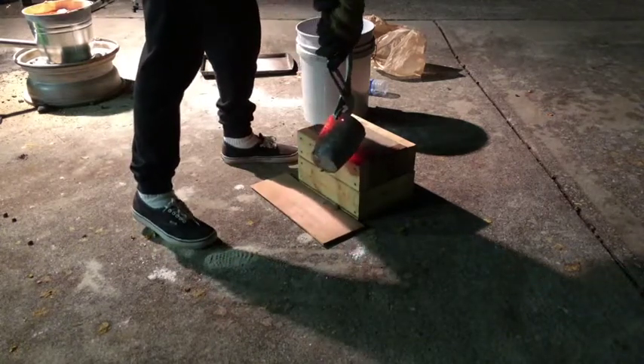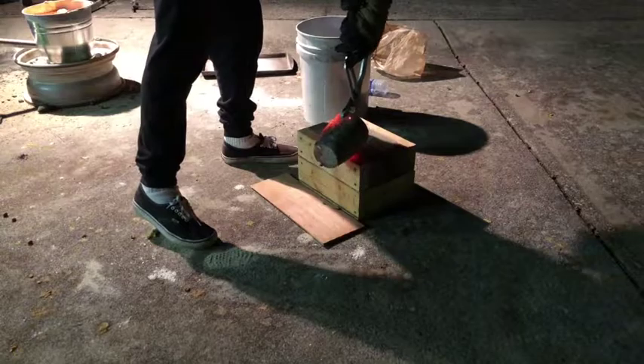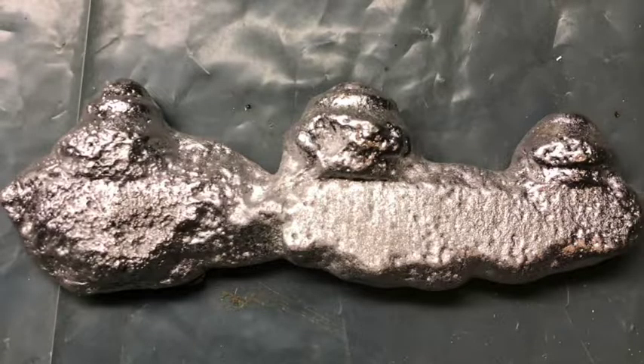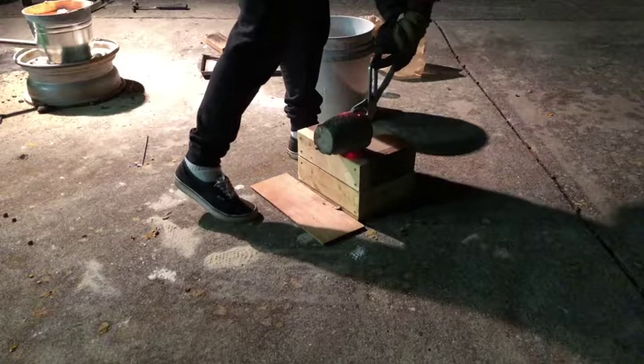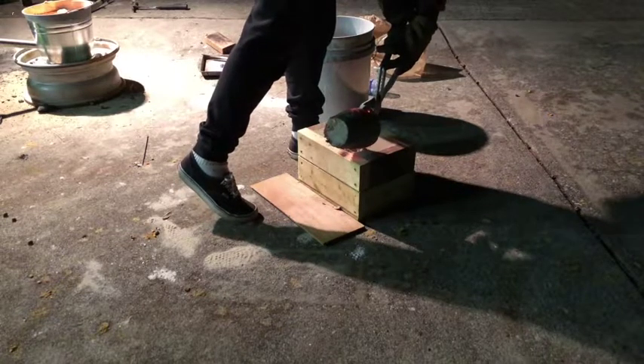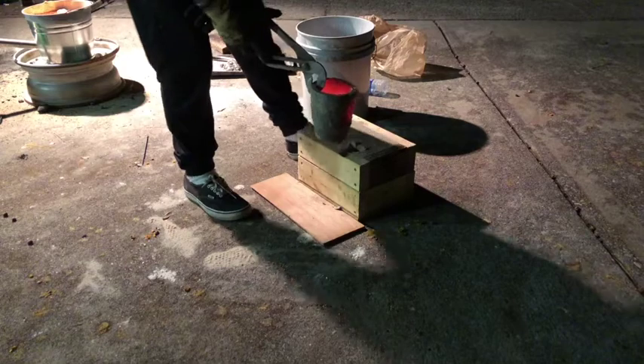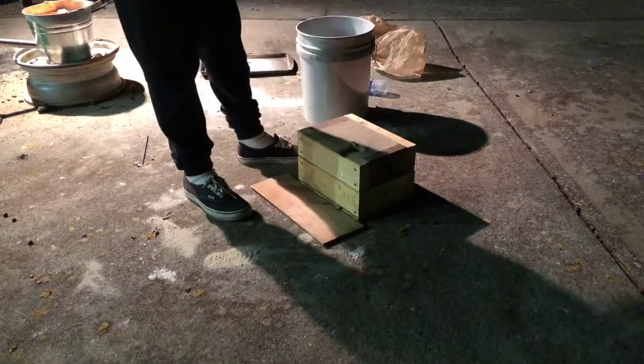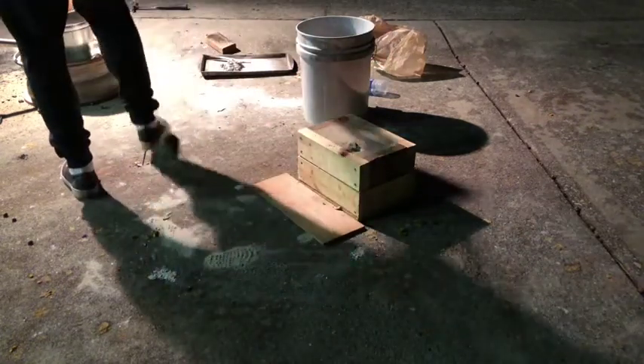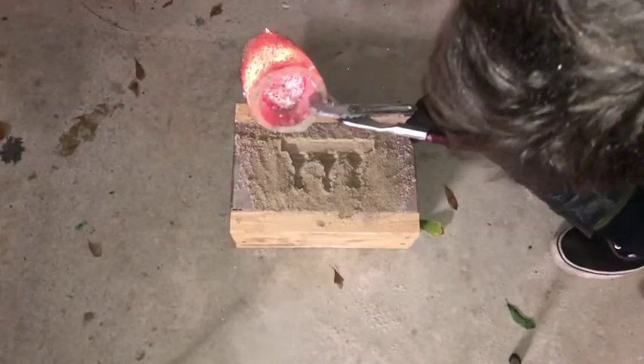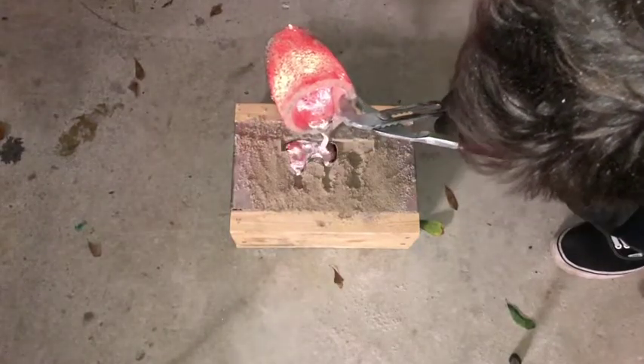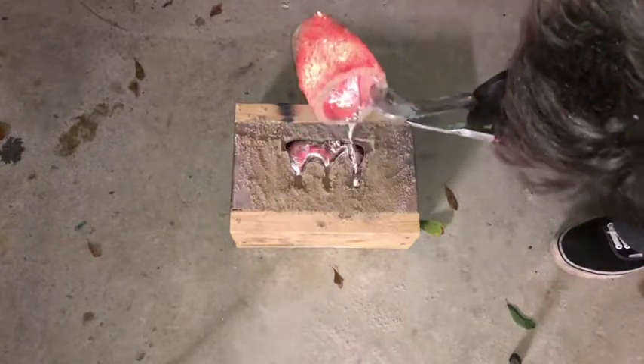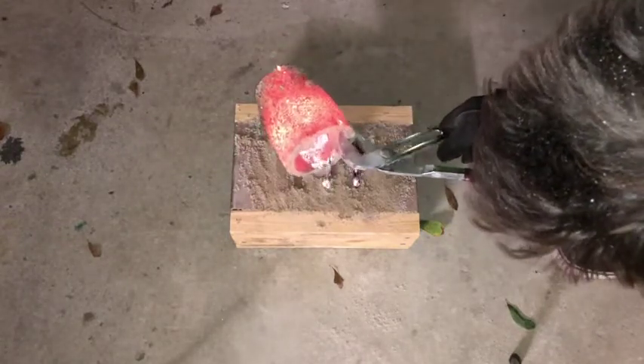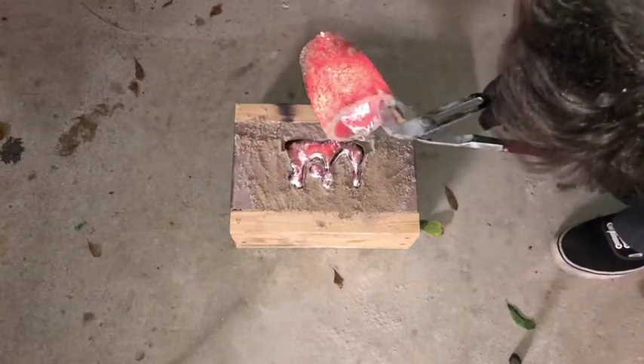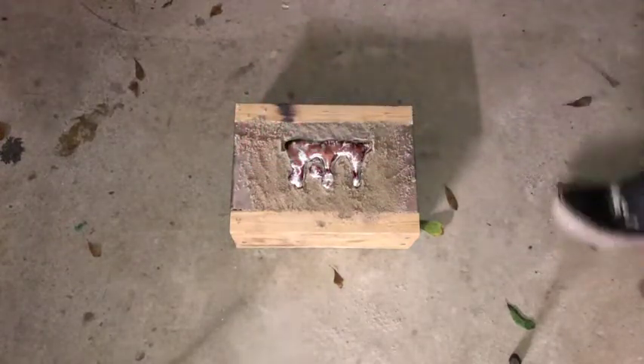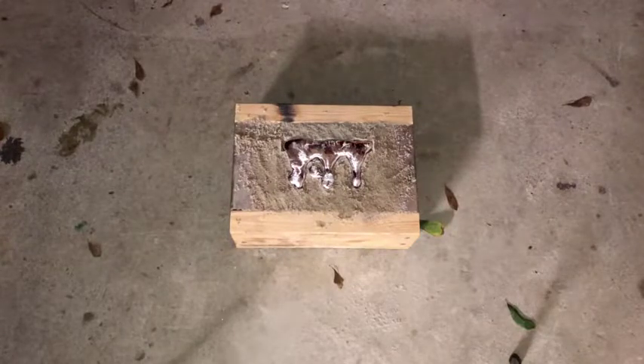In the first pouring, we quickly realized we did not have enough molten metal to fill the mold. Another issue we ran into was the top molds not staying in the mold boxes and instead collapsing onto the bottom, destroying the negative cavity of the pieces and ruining the cast. To compensate for this, we also tried pouring the metal into the molds without stacking them and without a sprue. This worked. It produced the best results on one side, but did not allow for the entire surface area of the chess piece to be created.